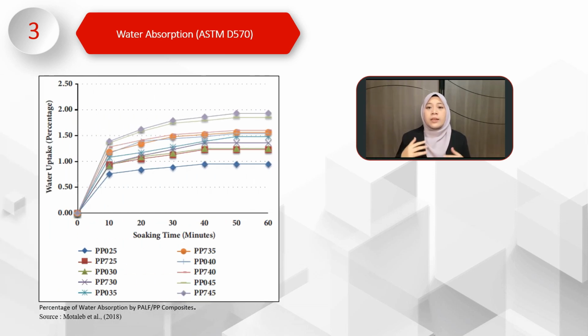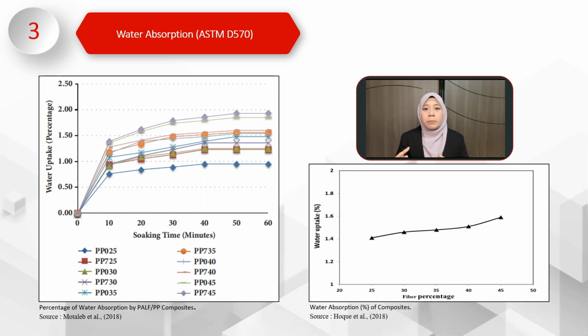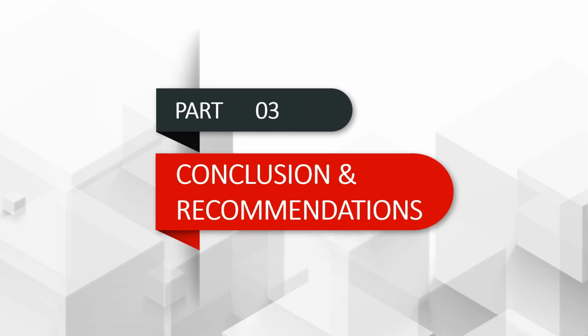Third is water absorption. The results of this study show that the percentage of water absorption rises with the rising soaking time. The rise in fiber content increases the water absorption percentage, as more absorbent areas are possible; they are more open places, created by the elimination of lignin and pectin, which lead to higher water absorption. Next, through the cutting edge of the samples, the composite absorbs water. Between 1.4 and 1.6% of water was absorbed by PALF PP composites. A higher amount of cellulose offers strong mechanical characteristics in the fiber, but it increases hydrophilicity, which results in increased water absorption. This is the last part, which is the conclusion and recommendation.